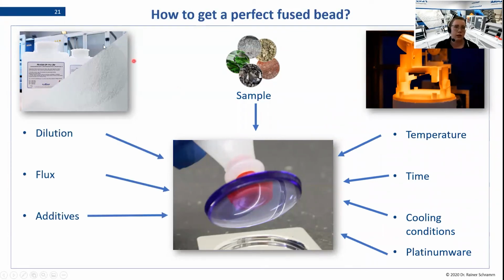And then on the preparation part, what we didn't talk about is the dilution. So the dilution also plays a big role in the preparation. And then, of course, what we talked about today is flux and additives, also two main parts that are important to get a nice fused bead. And we see this huge process here, and it doesn't even have all the different parameters that are influencing your fusion. And we only talked about those two today. So be careful and keep in mind that there's way more to the process than we just talked about.